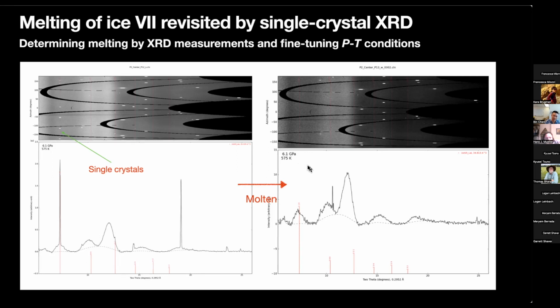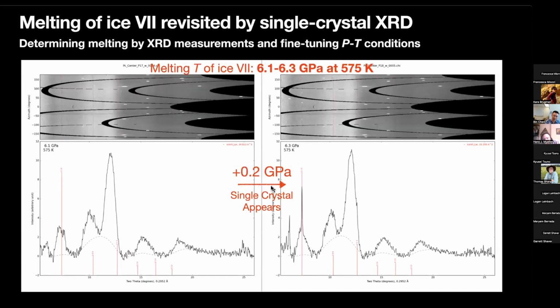Because our enclosure has this bidirectional pressure control, if we only apply some pressure, like 0.2 GPa, then we can synthesize single crystal. So we can really pinpoint the melting temperature of ice VII at 575 Kelvin. So at this temperature, the melting temperature is 575 Kelvin.